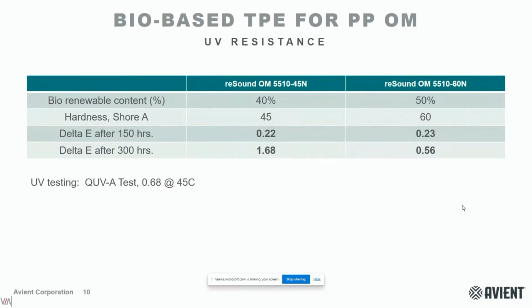After the UV test, you can see here two examples of the behavior and performance of these materials against UV. After 300 hours, the change in color is good, it's acceptable. So they have a good behavior in terms of aging against UV.